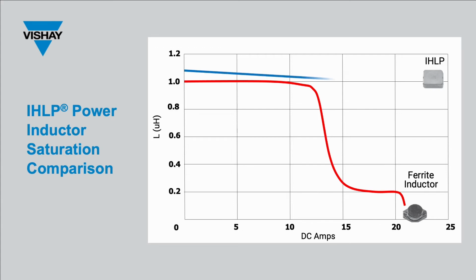In contrast, the blue curve illustrates the typical performance of an IHLP inductor. As the current is increased for a given value, the inductance decreases very slowly at a nearly linear rate, but never reaches a hard saturation point like the ferrite. This is a significant advantage in performance, knowing that your inductor will continue to behave like an inductor over the entire range of current. It also allows the power supply or filter to handle high transient current spikes without saturation, which improves the ruggedness and reliability of the system.